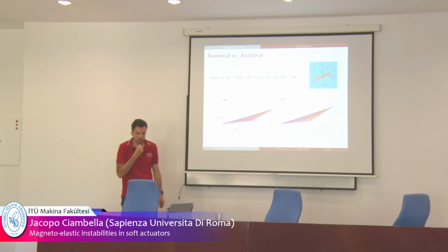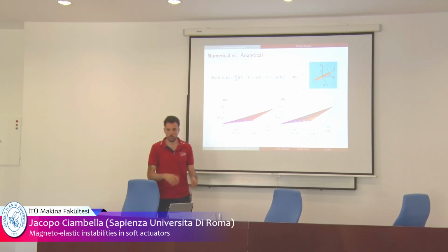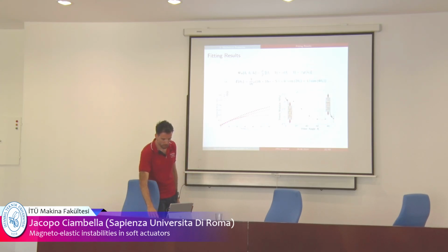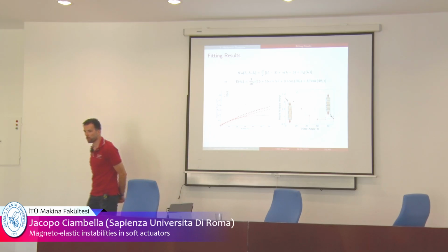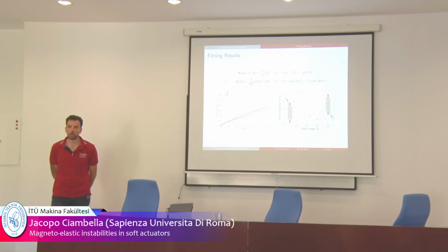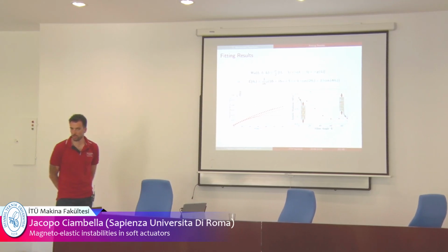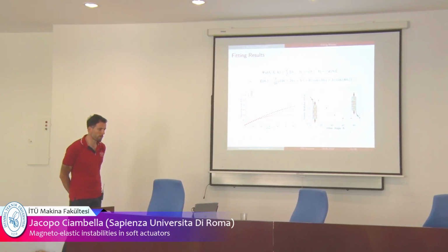And also the energy. Okay? We compare the macroscopic and the microscopic energy, so the energy predicted by the numerical simulation with the energy predicted by the model. Okay? And so these are the numerical simulations, and the plane is the analytical model, so there is a very good correspondence. So this means that you can use the model I showed you before to fit the experimental results without doing numerical simulations. So the analytical model will be enough.